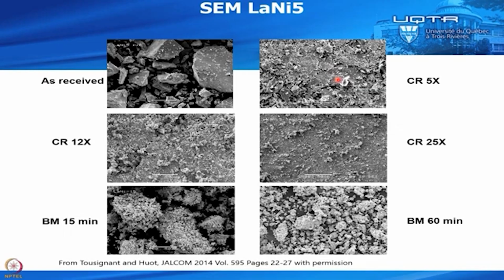And then we took this plate after rolling once, we take the plate, we fold it in two, and we roll again. So after each rolling, we have a reduction of 50% of our plate. Okay, so this is after 5, 12, and 25 roll, and you see the morphology of the plate do not change so much. But of course, we will have reduction of crystallite size and strain because after every roll we reduce the thickness of that plate by 50%.